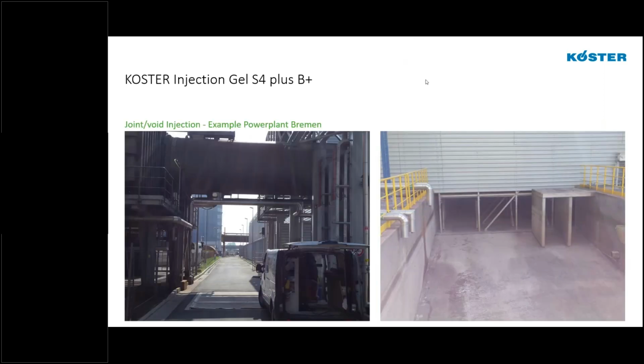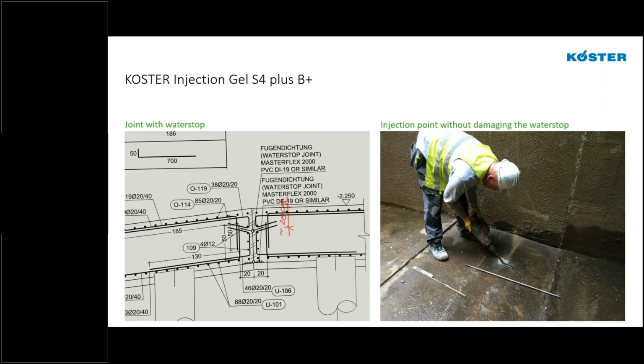Here's an example of the injection of the S4 with the B+ additive at a power plant in Bremen in Germany. We have our joint and that drawing on the left with our water stop installed. So we don't want to rupture the existing water stop. We inject the material behind the existing water stop to fill that void and to prevent any water ingress from occurring. So again, we're drilling to inject without any damage to the water stop. We're drilling behind the water stop to inject.